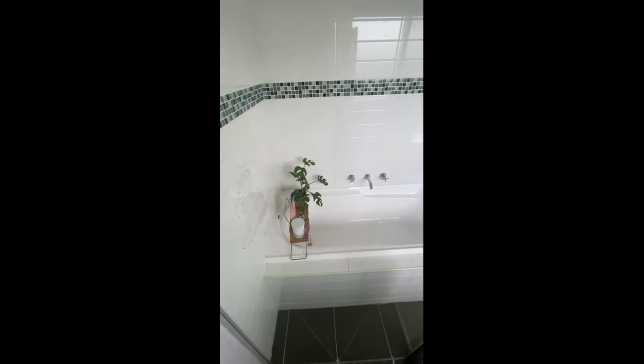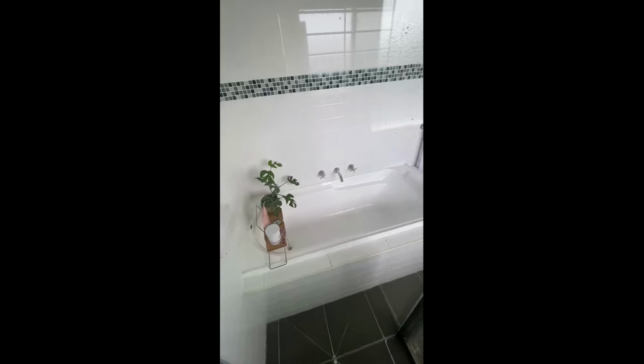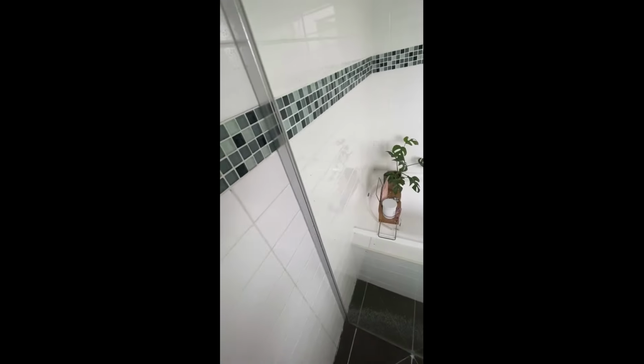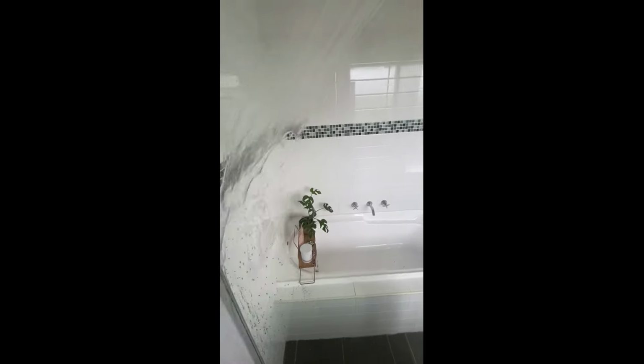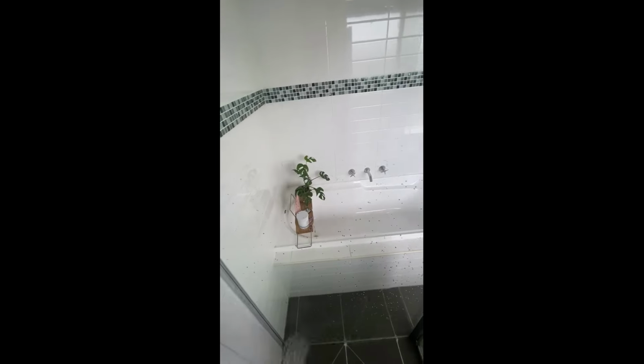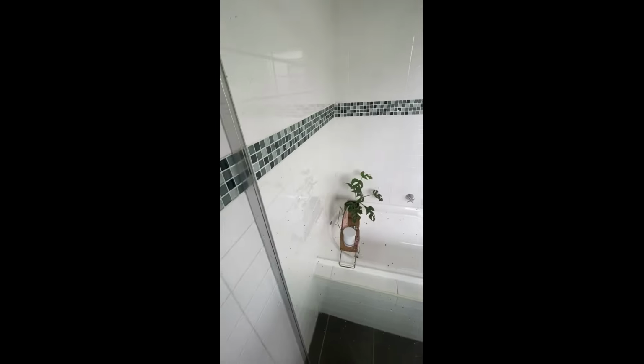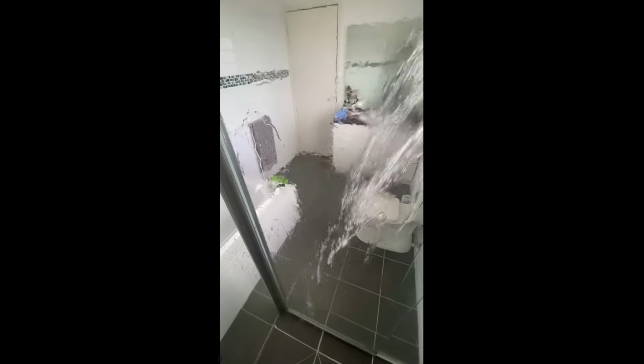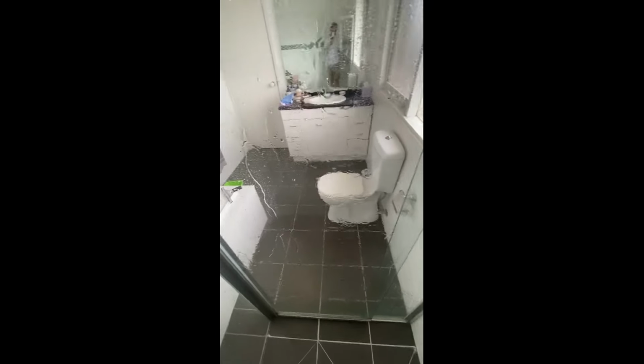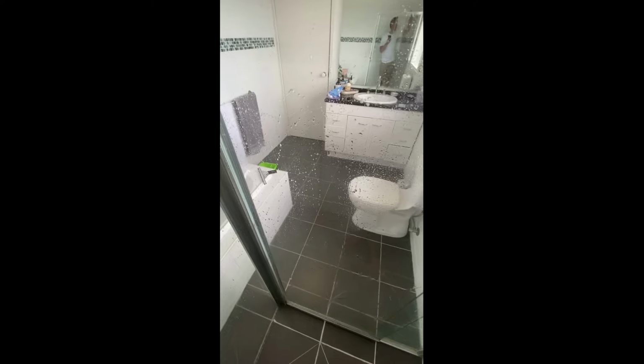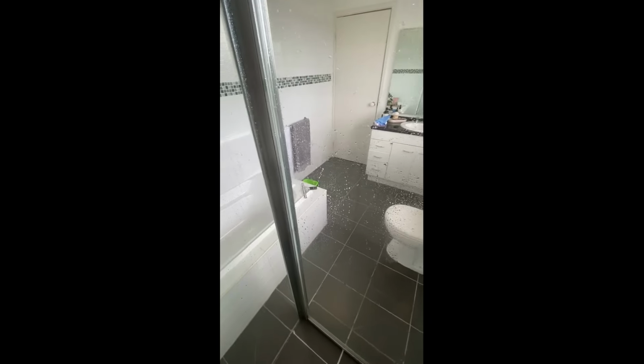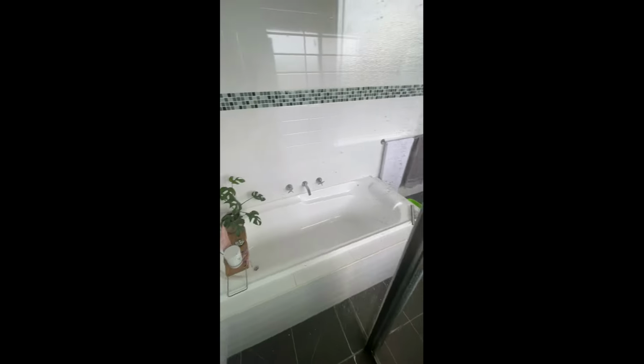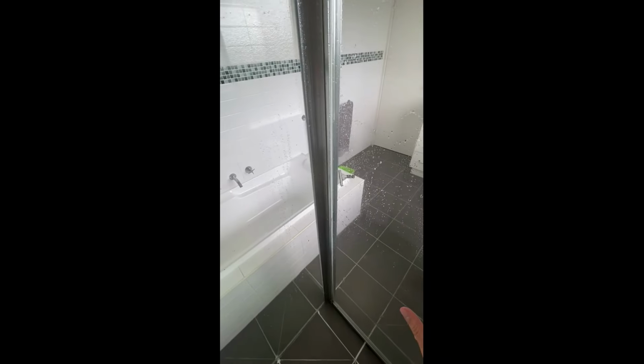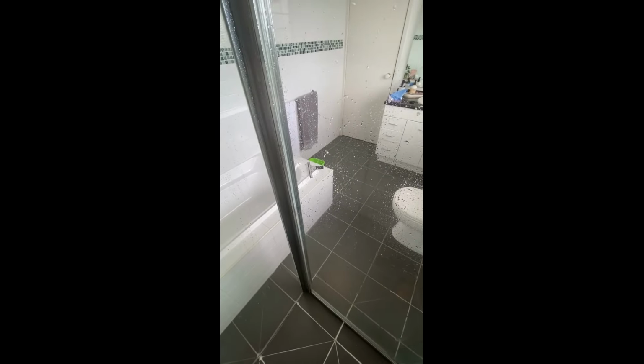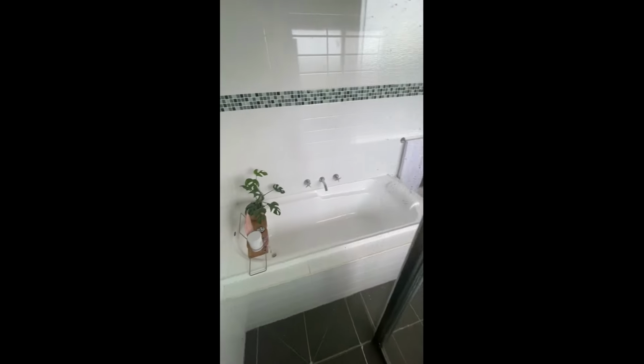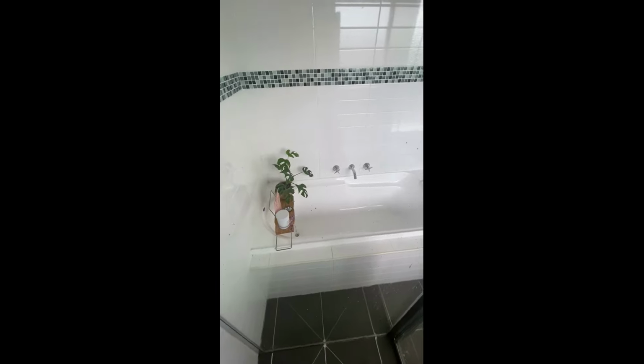There's another comparative. We'll give you a difference between the treated panel and the untreated panel with running water on it. So this is your treated panel, and as you see, the water just runs off, and it's obviously a nice clean panel, whereas on the untreated panel, again, the weight of the water will help it run off, but as you can see, there's all the contamination and dirt sticking to the glass still, which is all these droplets here, whereas everything here is just running away. So quite a different surface here, and that's where dirt and grime is just going to continue to build up on the untreated glass, whereas the treated glass, nice and clear, nothing sticking to it to maintain contamination.